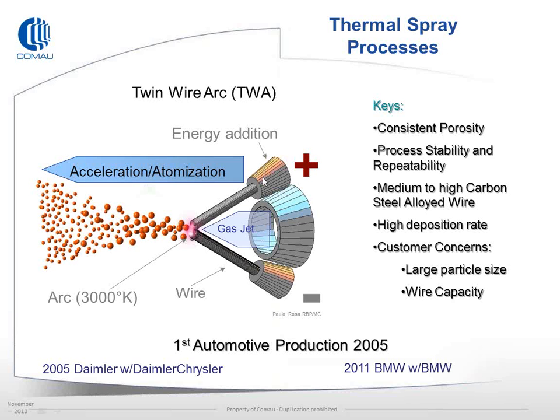Basically here you have two wires, one acting as the anode, one as the cathode. You're creating an arc between the two. It has roughly a 3,000 degrees Kelvin arc, much smaller. You end up with slightly larger particles here. Your gas jet is typically nitrogen based. This allows them to pick up the wire and maintain a stable arc. Atomization again, and acceleration of the particles, is created by the gas jet that's fed from behind the arc point.